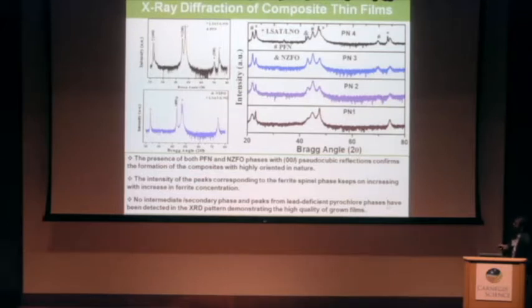These are the X-ray diffraction patterns of pure PFN, pure NZFO, and the composite structures. In PFN and NZFO, we only observe the L00 peaks: for PFN we only observe the 100, 200, and 300 peaks, and in NZFO we only observe the 400 peak. In the composite case, we also only observe the L00 peaks. In the composites, we observe both phases, with the H peaks corresponding to PFN and the N peak corresponding to NZFO. So we observe both PFN and NZFO peaks, which tells us the composite structure has formed.